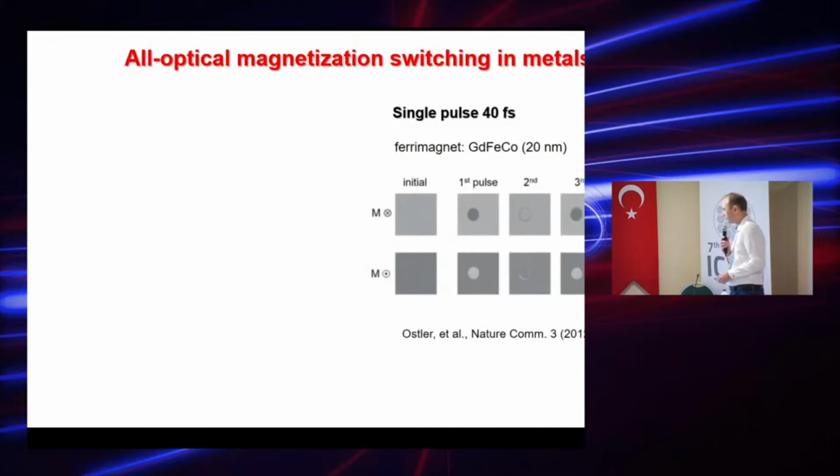Recently, a novel possibility was demonstrated: full reversible switching of the magnetization using a laser pulse in a metallic system. You can see in the magneto-optical images the switching of the domain. The contrast corresponds to the perpendicular component of magnetization in opposite directions in these images, and the switching depends on the initial state of magnetization and the number of pulses.